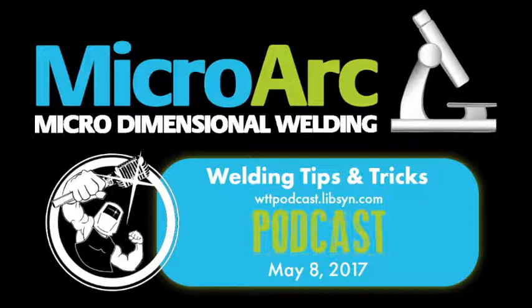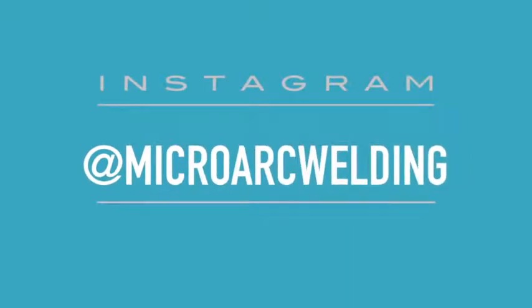What has this block been through before I've seen it? Has any other welder got a hold of it? What tempering temperature has been done? And we deal with a tremendous amount of geometry problems, where you're welding down inside a pocket and there's a sharp corner next to a rib. Right off the bat, I look at it and say, okay, the weld's going to pull. It's going to affect this other detail. Then you got to find a way to stop that weld where you're not creating this domino effect.